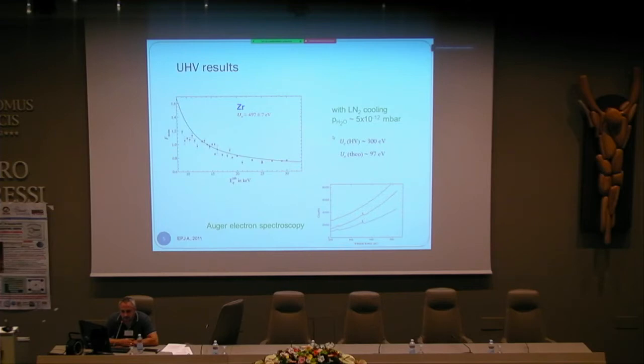It depends on many factors such as temperature and, maybe mostly, target contamination, and that's why we have a special system where we can get very good vacuum, almost 10 to minus 12 millibar.